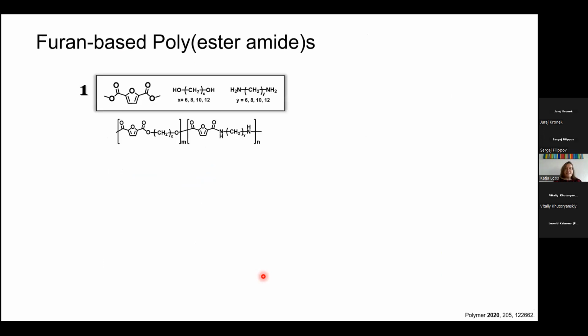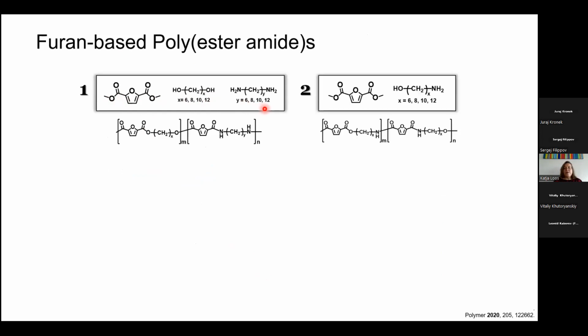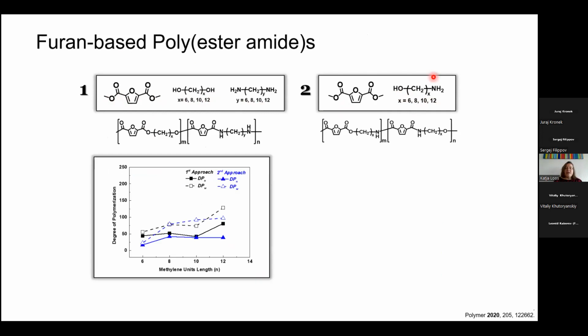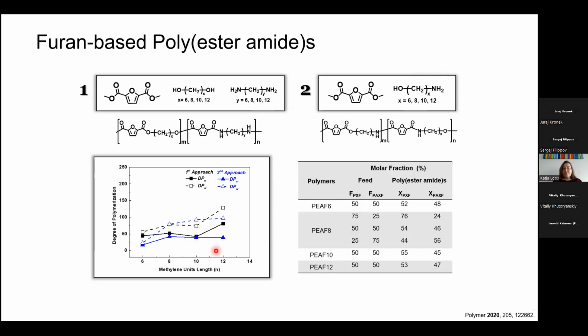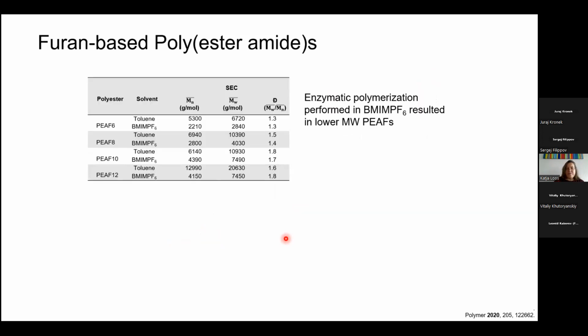And really the last thing I want to show you are the polyester amides that we recently synthesized. So of course you can have the FDCA and co-feed it a flexible diol or diamine, or you co-feed it a hydroxyamine. And yeah, we did both, and we look in 1-step, 2-step bulk solution. We always do that, and again we see dependence on different methylene unit chain lengths. But the reason why I wanted to show you that, and I don't want to go into detail, is that we actually do that in ionic liquids, and that's not on this slide.